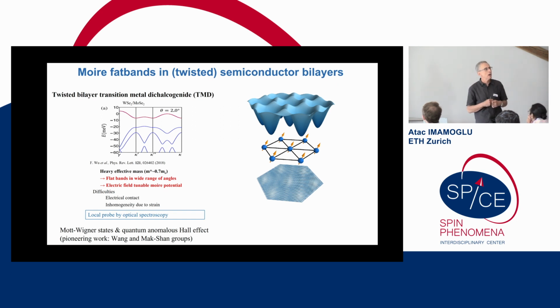a structure. But thanks to Shahal Ilani's brilliant development or invention, this can really become a tuning parameter at this point. And the applied electric field can be used to tune the moire potential. The difficulty is that it's very hard to get good ohmic contacts onto these materials, so one really relies predominantly, although not exclusively, on optical spectroscopy. And much has been achieved, and the pioneering work of Feng Wang and the Mak-Shan group at Cornell has to be mentioned. Much has been observed, and most recently, fractional Chern insulator states have been reported. I should also add Xiaodong Xu in that sense.